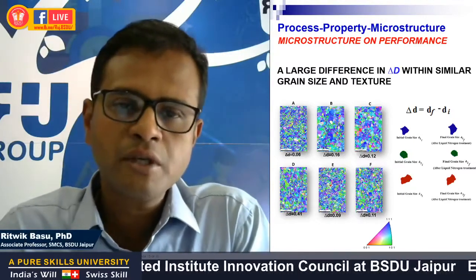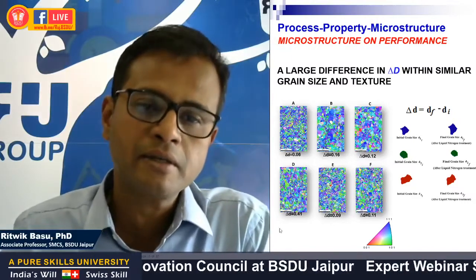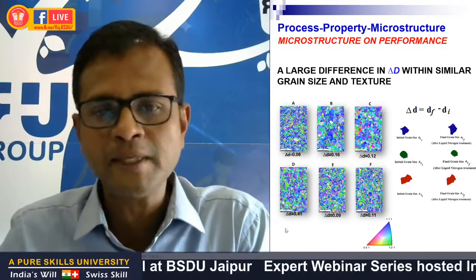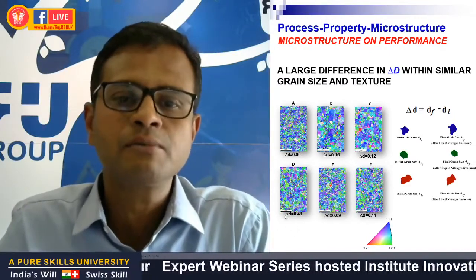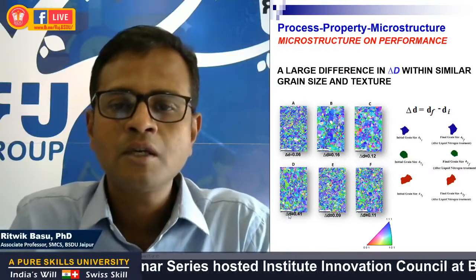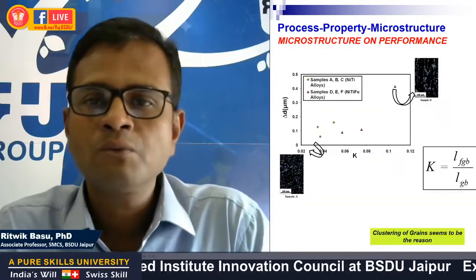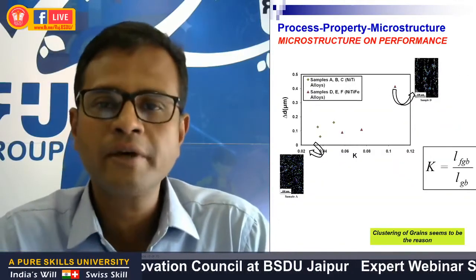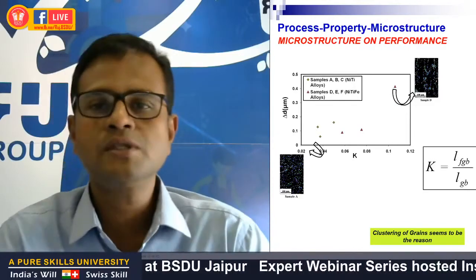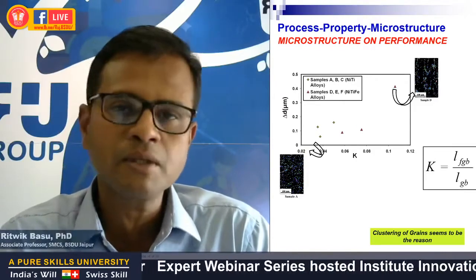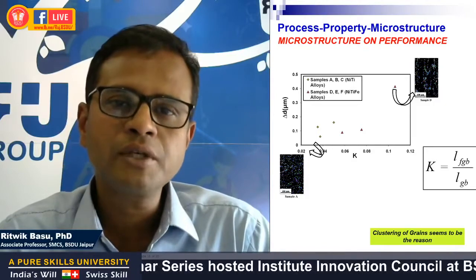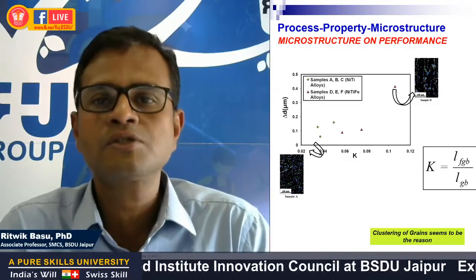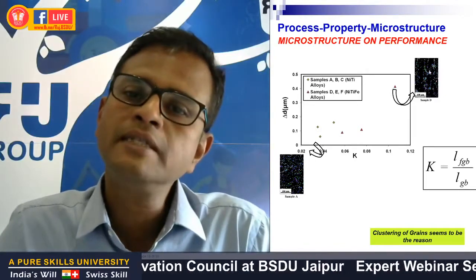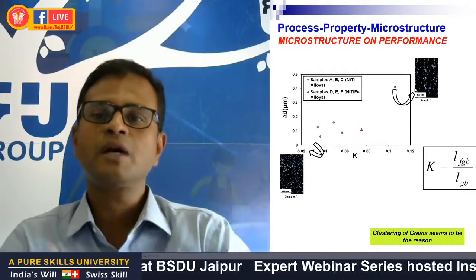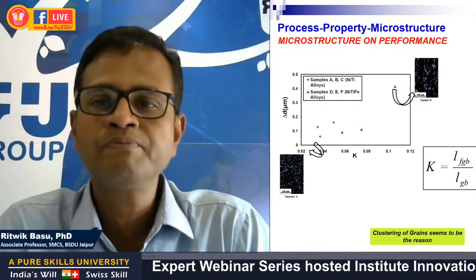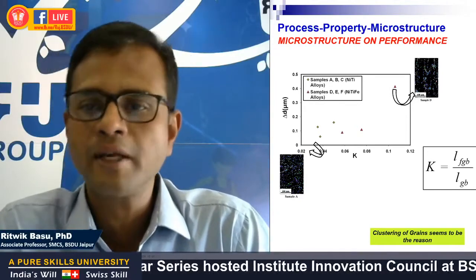So the question here is, why should sample D exhibit such an aberrant value? Here sample D is the bad guy. That means it shows the highest irreversible strain, and this is not a preferred microstructure. So why? To answer this question, we had to look into the microstructures very carefully for all the 6 different samples. Although all these microstructures more or less resembled each other, a careful look showed that all of them had a distribution of fine grains. However, sample D showed the largest clustering of the fine grains. So the answer to why sample D shows such an aberrant value lies here. It is largely because of the fine grain clustering.